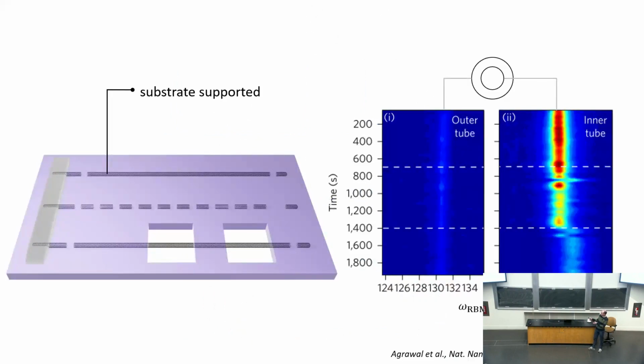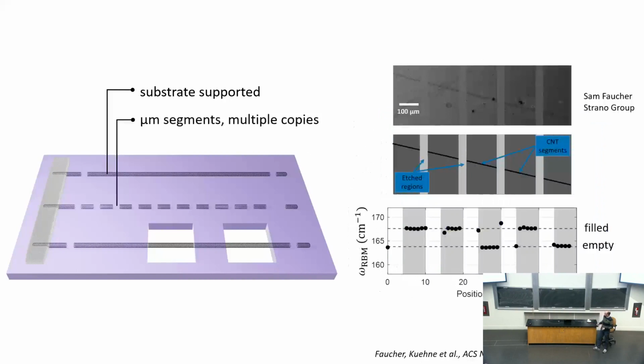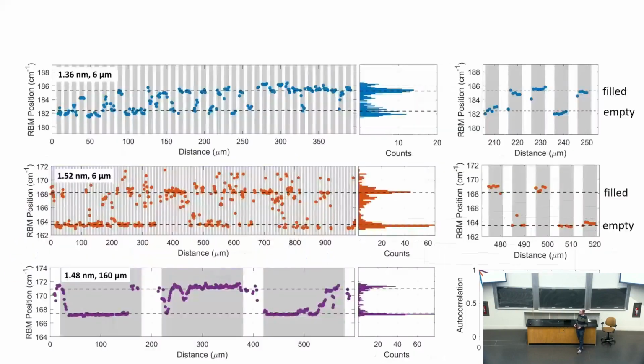The inner wall RBM is here, and they put water on the system and waited for water to come into the spot that was probed in Raman. You see at a certain point this upshift, which corresponds to filling. We have innovated this platform by segmenting these CNTs, so we get physically separated entities of the same pore, which is very powerful for reproducible nanofluidics. You can have the same system and probe it over and over again. Some of them will fill when you put them in water, and some will remain empty, so you have a built-in control of filled and empty systems.